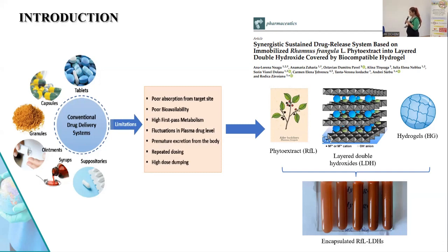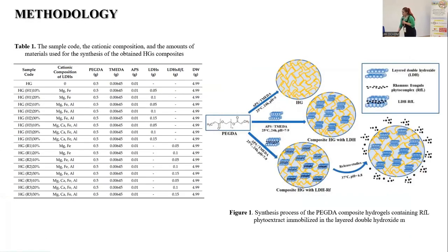the intercalation of the layered double hydroxide inside the hydrogel, the layered double hydroxide having been previously encapsulated with the Rhamnus frangula phytoextract, obtaining the encapsulated hydrogels. So the synthesis of the composite hydrogels is based on in situ polymerization in aqueous solution, with polyethylene glycol diacrylate, and initiated with APS, ammonium persulfate aqueous solution, and